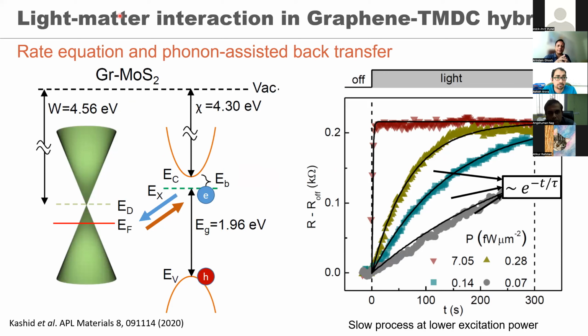All we have found is that the binding energy we estimate from such optoelectronic functionalities is consistent with that obtained from photoluminescence measurements. However, our method is not accurate enough to say whether having graphene nearby changes the binding energy much. Some reduction is expected because of screening, but we cannot comment on that.